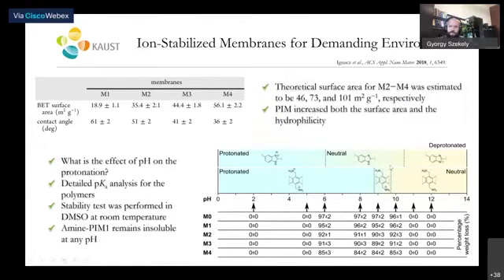However, in a mid-range pH, when we go from 6 to about 10, and for the other polymer, let's say 9 to 10, then PBI is in a neutral form, and only one of the amine groups of the PIM is protonated, and this allows the membrane to be soluble. And therefore, here you can see that in this pH range, you're losing your membrane when you're performing a separation. So these membranes should be used at lower or higher pH.